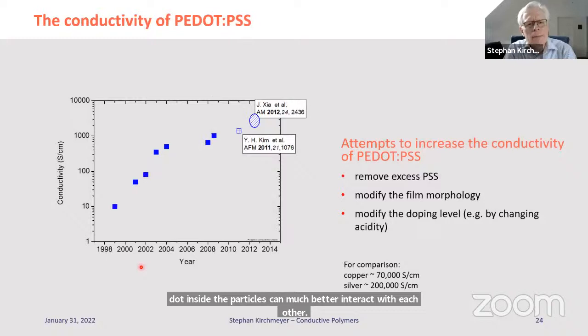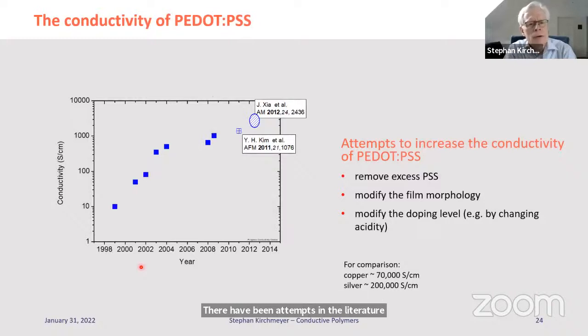There have been attempts in the literature to make the conductivity as high as possible, and there were reports with more than, let's say, 3,000 to 5,000 Siemens per centimeter, which is a material specific value. Commercially, approximately 1,000. To compare this to real conductors, 1,000 compares to copper at 70,000 or silver at 200,000. So they are conductive. They are nicely conductive, but definitely much less than metals.